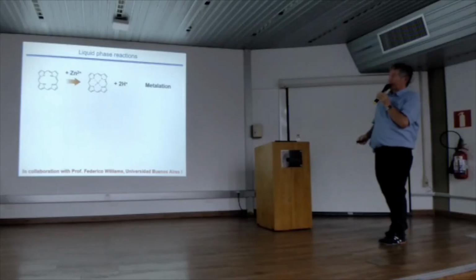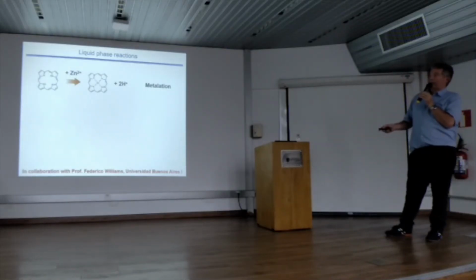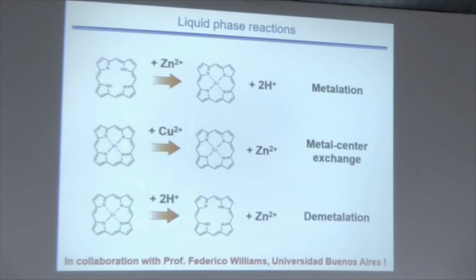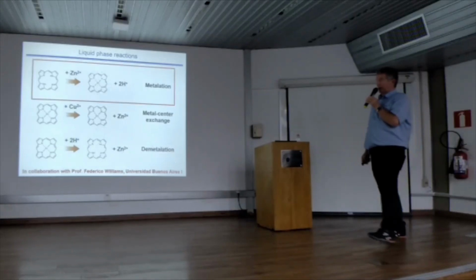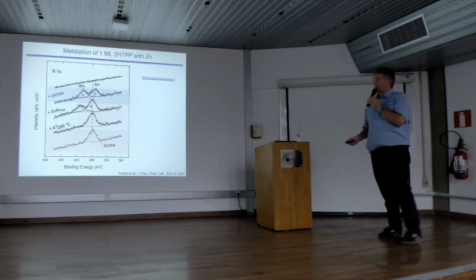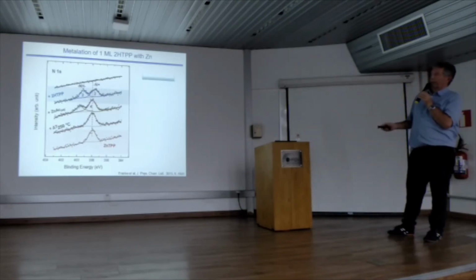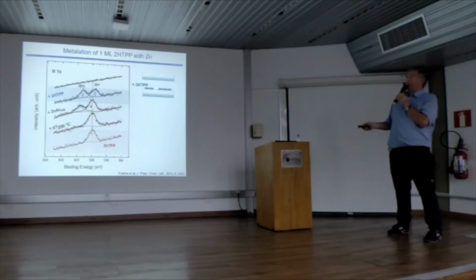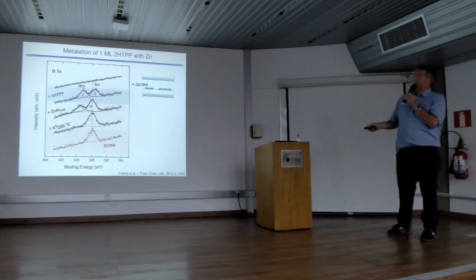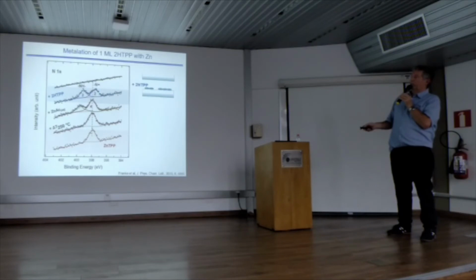And we studied three reactions. The first one, metallating a free-base porphyrin with zinc. The next one, removing the zinc and replacing it by copper, so exchange. And the last one is getting out the zinc and getting back to the first one. That's demetallation. Concerning metallation, this is the result of the experiment. We start out with the clean surface, so there's nothing on the surface, flat background. Then we adsorb the free-base porphyrin in vacuum. We have the well-known two peaks, so we have our porphyrin on the surface.